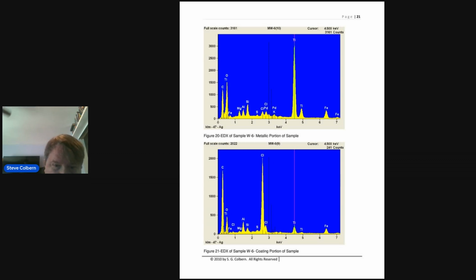I did two EDXs here on W6 because I wanted to show the difference between the surface coating and the metal. The W6 obviously had a coating on it, and I'm not sure why there was that big titanium peak in the EDX here. There wasn't too much titanium in these samples. That must be an artifact of some kind. Palladium showed up in this sample, and that's very strange. And a lot of chlorine in the coating part of it on the bottom, and there was sulfur. So chlorides and sulfates, perhaps. Next page.